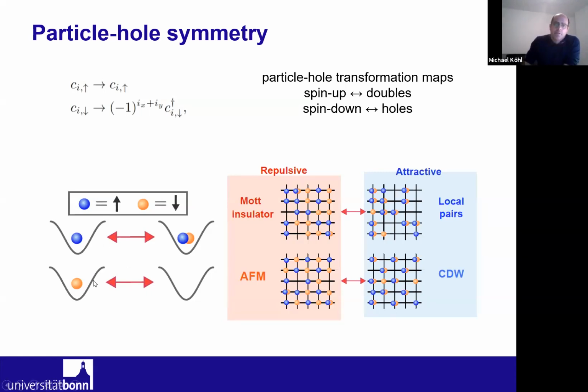So here's the pictorial visualization. We say blue is spin up and red is spin down. Then this transformation converts spin up into doublons and spin down into holes. So if we accept that, what happens then to our phases if we do this particle hole transformation? Let's say we start out here from this Mott insulator, which has on average 1 particle per site, and there can be the occasional fluctuation like here or like here, but it has pretty uniform occupation. And wherever we have now a spin up particle, we get a doublon after the transformation, and wherever we have a spin down particle, we get a hole. So that would be basically a transformation of a Mott insulator into a gas of local pairs.